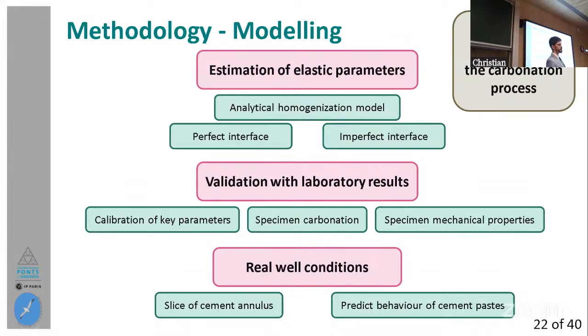For achieving that objective, we have gone first to an estimation of elastic parameters, which was done with this analytical homogenization model I have used, which was considered in 2 cases. The first one is the perfect interface condition, and the second one is the imperfect interface condition. Then I have done some validations with laboratory results, which was done doing some calibration of key parameters. Then I have modeled the conditions attained in the carbonation cell, and then I have validated the results obtained from compression, whether unconfined or confined compression tests.